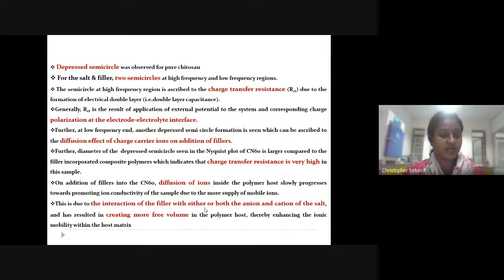two semicircles, at high frequency and low frequency. The semicircle at the high frequency region is due to the charge transfer resistance, which occurs as a result of the formation of the electrical double layer. Actually, Rct occurs as a result of the application of external potential to the system and the corresponding charge polarization at the electrode interface. Further, at the low frequency end, another depressed semicircle is formed, which could be ascribed to the diffusion effect of charge carrier ions and addition of fillers.